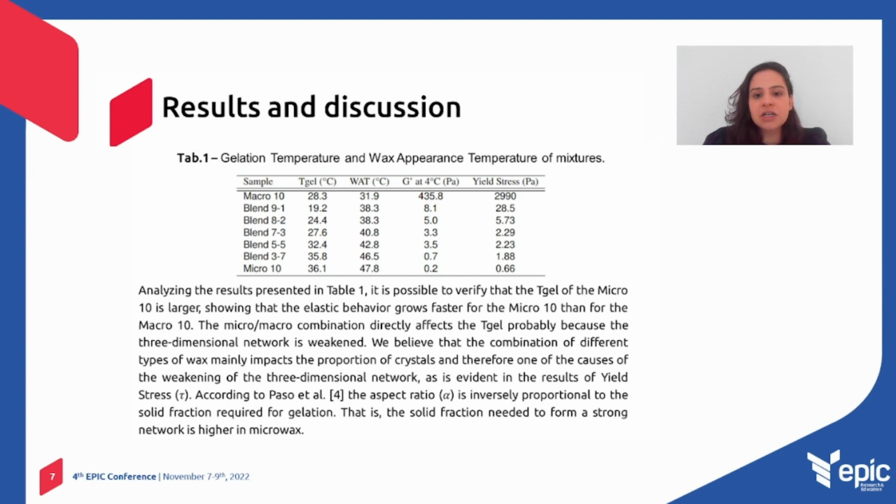So the addition of 1% of micro considerably reduces the yield stress. This makes clear that the type of wax impacts the weaker network of the mixtures.